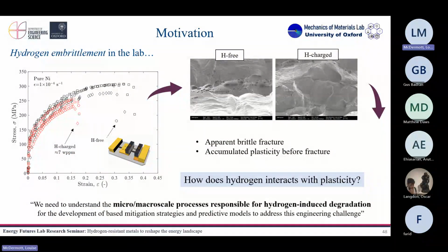So what we see usually is the same curve as I showed before. Hydrogen has an effect on my stress-strain behavior. Okay, so you can really see that it's making it more brittle. And if I go to an SEM fracture surface, I actually can see that when we have hydrogen, microscopically, we can see this brittle behavior, right? Characterized by intergranular fracture.